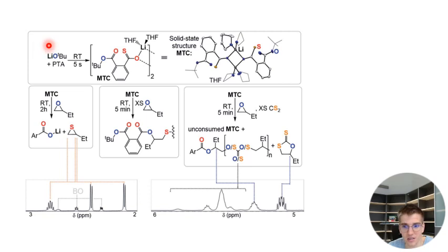So what I did, I just mixed stoichiometrically lithium tert-butoxide and the cyclic thioanhydride PTA, and formed this salt. It's just the ring opened thioanhydride with the original alkoxide here. And I crystallized it, got a crystal structure to see how the lithium is bonded to it. Of course, this is a crystal structure, right? So it's the solid state, so you never know how it's actually looking in solution. And also not only how it's looking in solution, but if it can transform into a less stable species in solution that is then more catalytically active. So you have to be cautious with looking at crystal structures as solution state structure or catalytically active species, but you can make some modest assumptions.